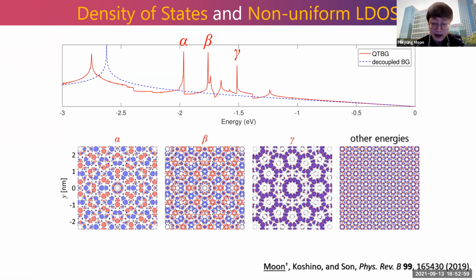However, I also showed, not in this paper but in the next paper, that we can use TMDC or other, even rectangular layers. For example, a rectangular layer stacked at 45 degrees gives an octagonal eight-fold rotationally symmetric quasi-crystal.